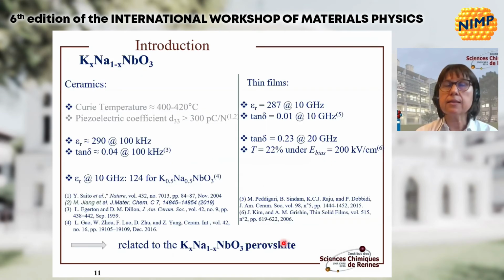So, in this context, the perovskite in the KNN system presents, beside the piezoelectric coefficients that are promising, a quite high dielectric permittivity in ceramics at moderate frequency, and that is still quite high at 10 gigahertz in ceramics. In thin films, there are only a few reports on thin films of KNN in high frequency. We can see, for instance, this paper dated from 6 years ago, giving epsilon R about 300 at 10 gigahertz and tangent delta of about 1%.